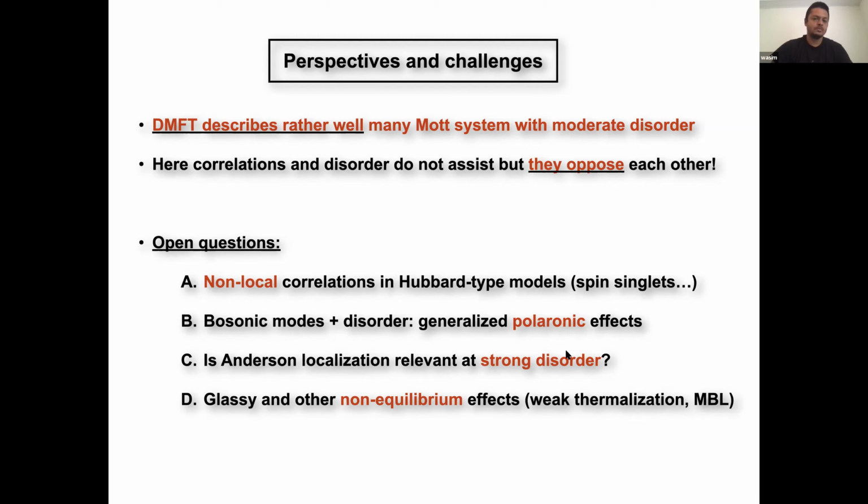Because of this, the superexchange interaction J is also broadly distributed, and there will be some bonds which have very large superexchange. So in that case, you find something reminiscent of VO2: the low-temperature spin configurations form pairs of singlets, which are randomly placed because of disorder. In principle, you can think of this as a very random version of VO2.